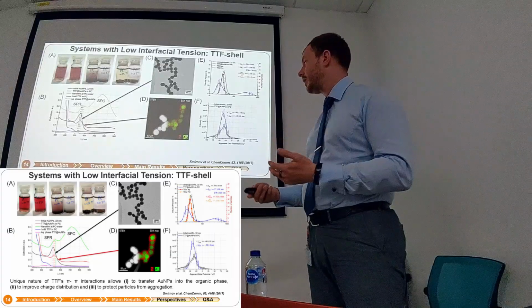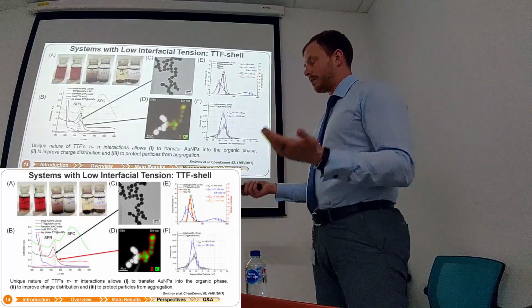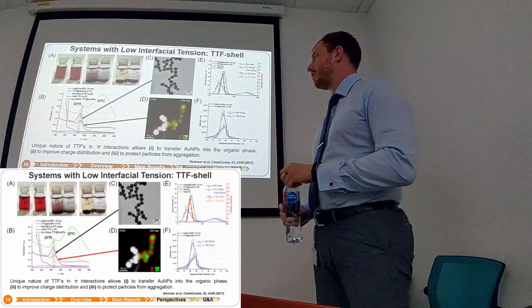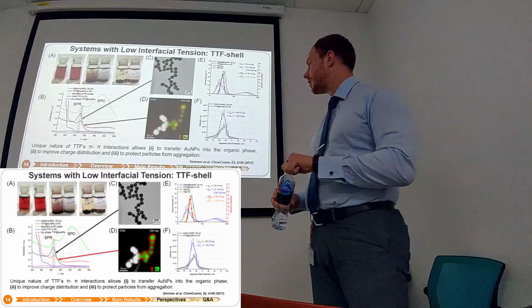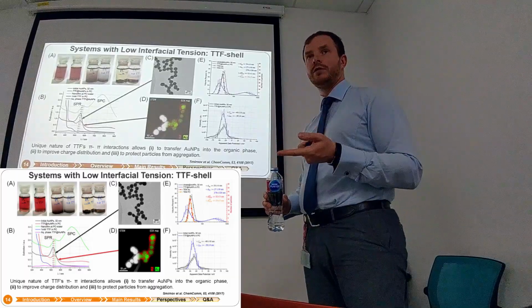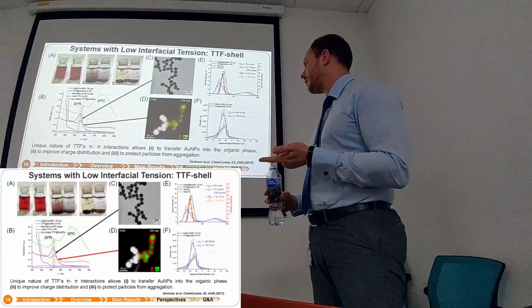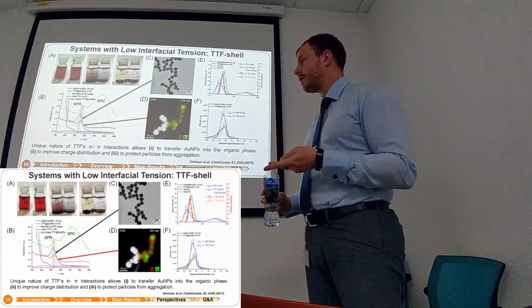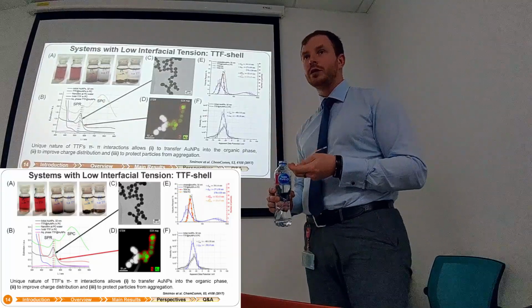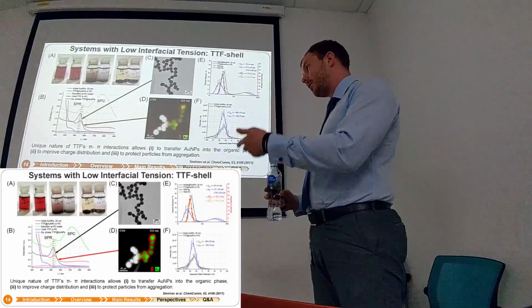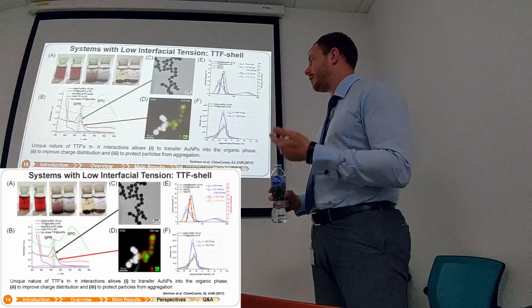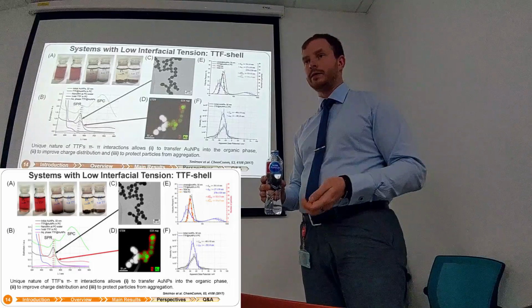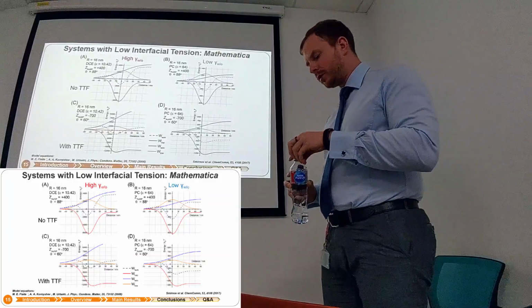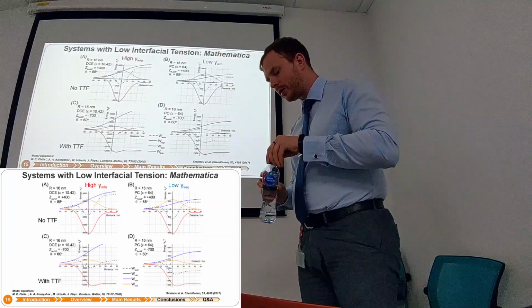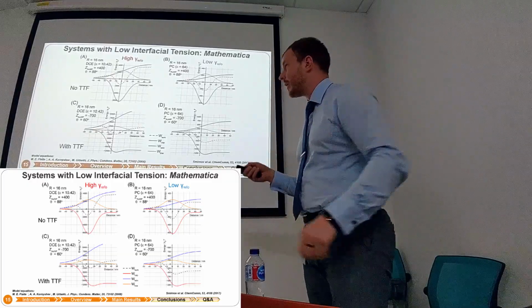really stable colloidal suspension. And again, the unique nature of TTF's π-π interactions allows us 3 things. It's a transfer of gold nanoparticles to the organic phase, then improved charge distribution, and this improves stability of this colloid, and then protects particles from aggregation. This is a small slide illustrating how it works in reality.